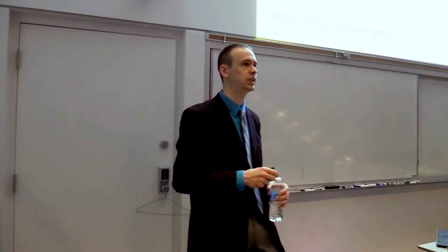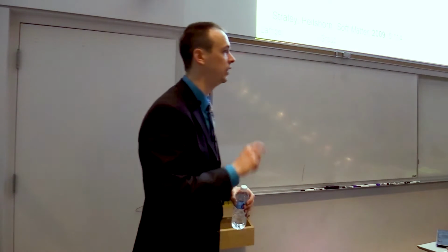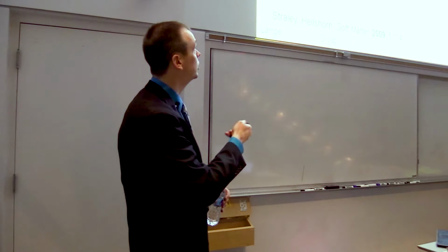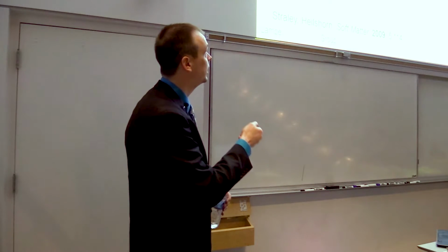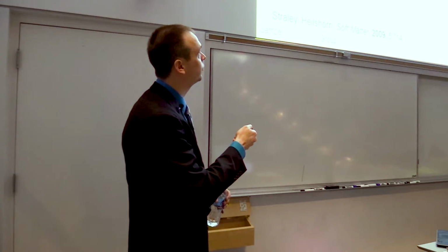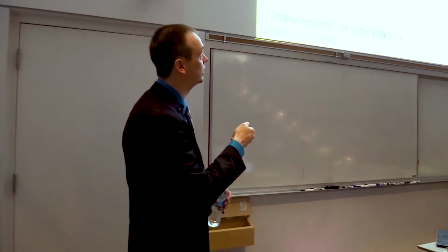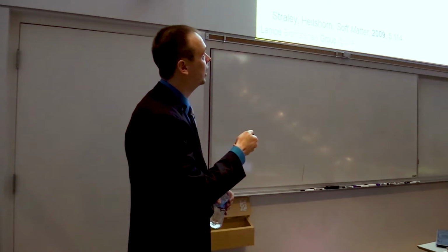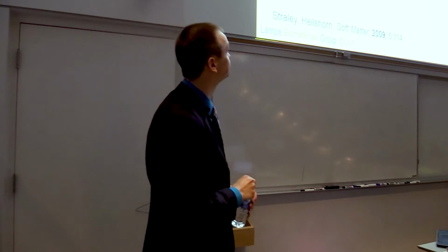So elastin is a protein that's found in the human body throughout a variety of different tissues, but you can think about it maybe where things are more elastic. So you find a lot of elastin in your blood vessels, right? That have to allow pulsatile expansion and compression, right? So an elastin-like block, and you can see the sequence here. It has this repeat structure, VPG, and I'll say XG, right? And every once in a while, we'll have an isoleucine there. Sometimes we'll have a lysine, but mostly isoleucine, right?